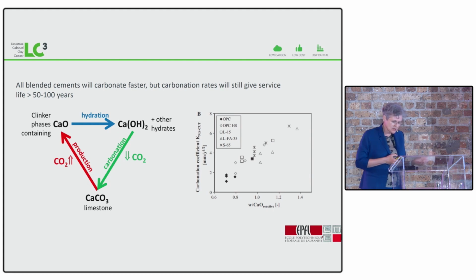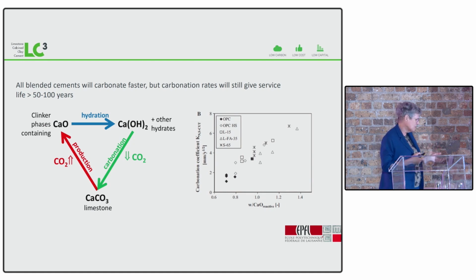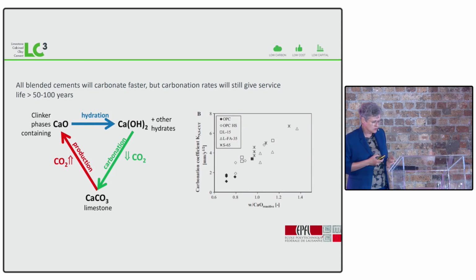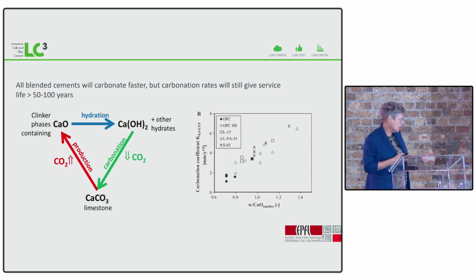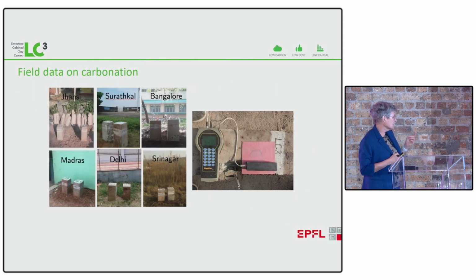In terms of carbonation, well, there's no such thing as a free lunch. The whole point we've been trying to work on is to reduce the amount of limestone, which is giving off CO2 in the first place. And that inevitably means there's less capacity to absorb CO2 afterwards. So low carbon materials will carbonate faster because they contain less buffer. But the important thing is that what happens with LC2, LC3, is exactly the same as you have in fly ash.